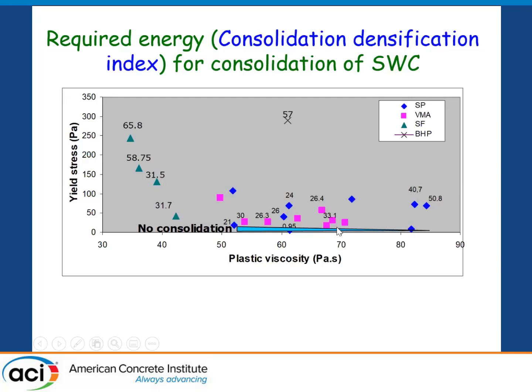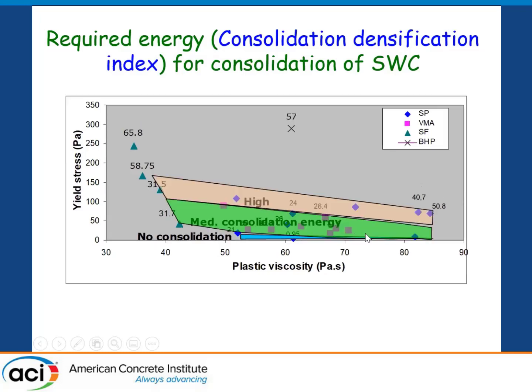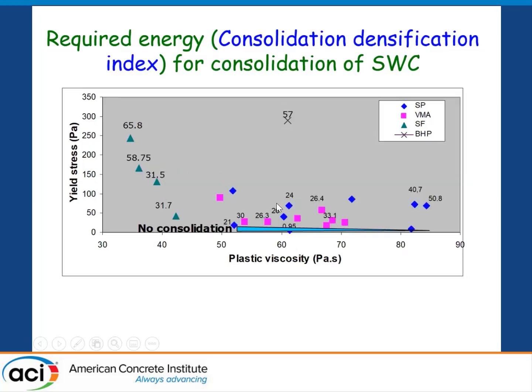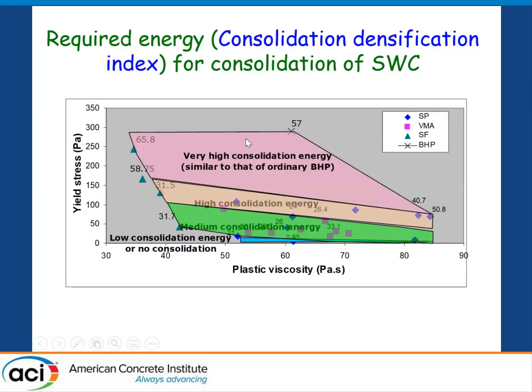Very little energy is needed for SCC. But then if you make your concrete super workable, you reduce the slump flow, you need medium consolidation, reduce it further, you need high consolidation, you reduce it even further, reaching the lower end of the super workable concrete, you need very high consolidation. So you could look at your yield stress versus plastic viscosity, and what you have inside is the amount of energy that is needed to consolidate the concrete. And you can see that there are four regions. 3 of them are for the super workable concrete versus the SCC.